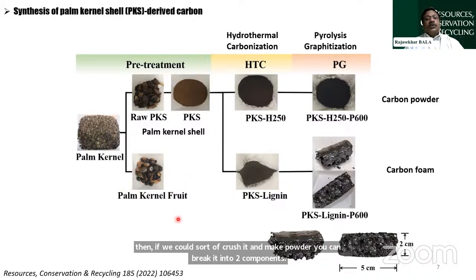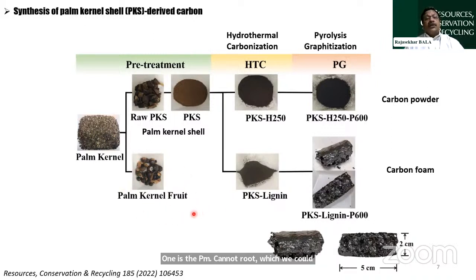In this instance, we used palm kernel, which is a product that you get from the palm oil industry, which is increasing in numbers these days in the interest of producing palm oil. And you get some byproducts, and if you crush it and make powder, you can break it into two components. One is the palm kernel fruit, which we could use to make bio oil, which I'm not going to talk about. Instead, of the powder you get, that's a palm kernel shell. It can be pre-treated by adding water and then drying it at about 60 degrees Celsius to get rid of the moisture, some impurities, and so on.